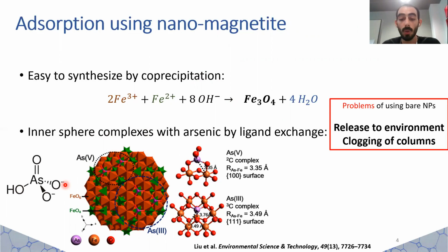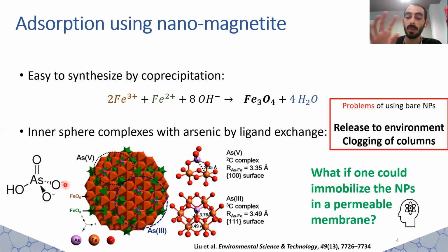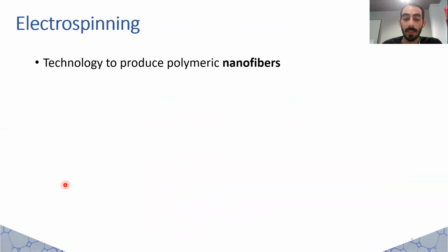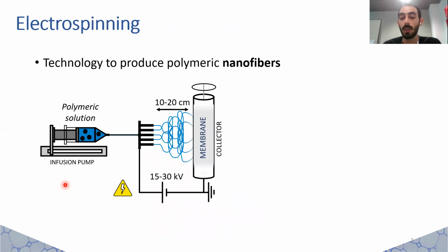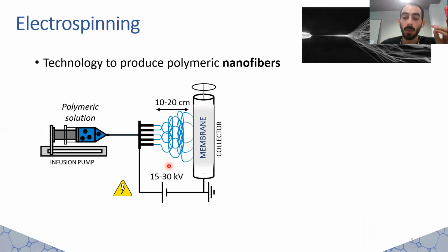But what if one could immobilize the nanoparticles in a permeable membrane? This is where electrospinning comes in. It is a technology to produce polymeric nanofibers, in which a polymeric solution is injected through a needle nozzle pointing at a rotating drum collector. When the nozzle is connected to high voltage, the solution charges and the electric field pushes the solution towards the grounded collector, like can be seen in this picture. During the flight, the solvent evaporates and solid nanofibers are deposited.